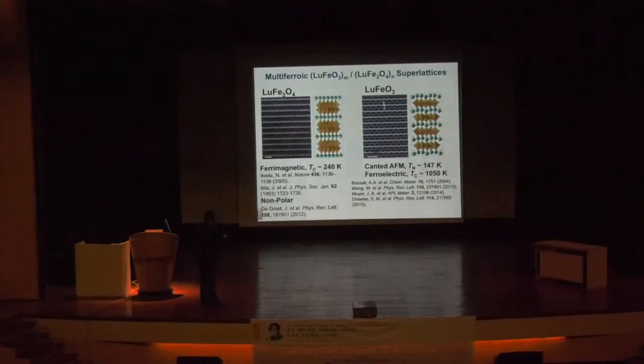Now, these two guys are atomic resolution images, and you can clearly see where the polarization is going to come from. You can see the 2 lutetiums up, 1 down. So it has a 2 up, 1 down, 2 up, 1 down, structural distortion. So lutetium iron oxide 113 is called an improper ferroelectric, meaning the primary order parameter is not a charge degree of freedom, but a structural degree of freedom.